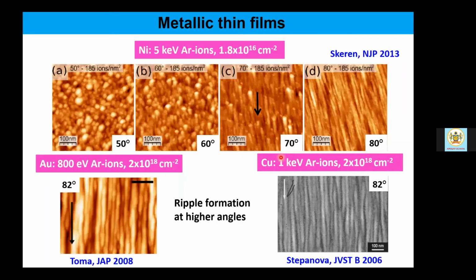And now is the turn of metals. Metal doesn't remain behind. So, for instance, here we are talking about pattern formation on nickel thin film using 5 keV argon ion at an ion fluence of 1.8, nearly 2 times 10 to the power 16 ions per square centimeter.